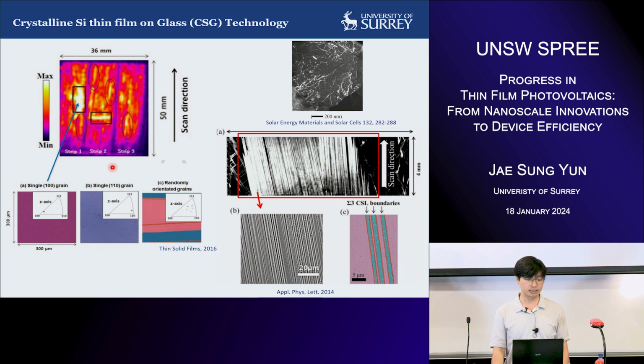we found that there is actually a grain orientation dependence, which changes the lifetime of the carriers. Also, if you have a random crystal orientation, it gave us bad performance and bad carrier lifetime. My colleague Jae Sung Yun has done very nice work on finding out what the problem is with this crystalline silicon thin film, and there happen to be a lot of dislocations within the grain. You can see that this is a TEM image. You can see a lot of defects, intragrain defects inside the crystal grains.